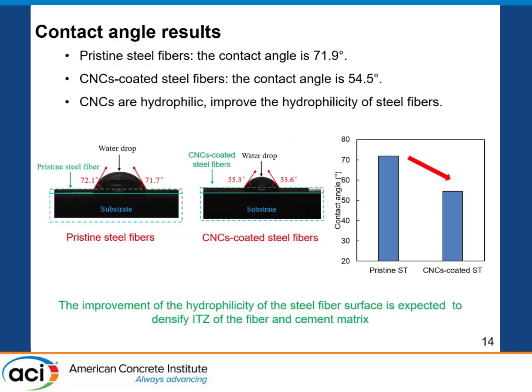Also, by this coating process, we decreased the contact angle from 71.9 degrees to 54.5 degrees, which means we changed the surface of the steel fibers to be very hydrophilic. This hydrophilicity improvement is important because it will be beneficial for densification of the ITZ between the fibers and the cement matrix.